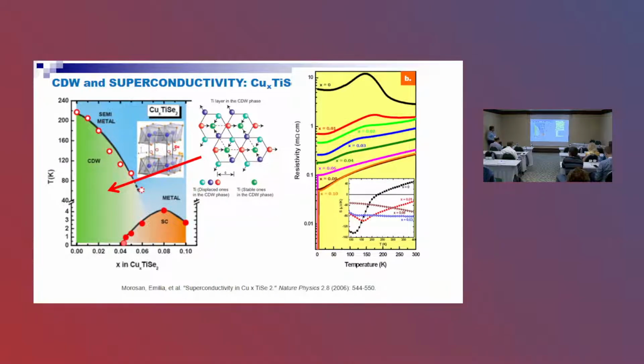So how do we see that charge density wave? Basically, if we consider the pristine compound and look at the temperature dependence of the resistivity, it goes more or less semiconductor-type up to a peak, and this peak corresponds to the charge density wave transition. That was how people first found this. In principle, this is a structural transition, which we see in X-ray.